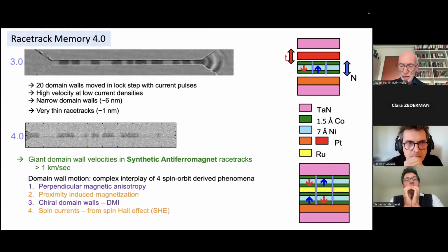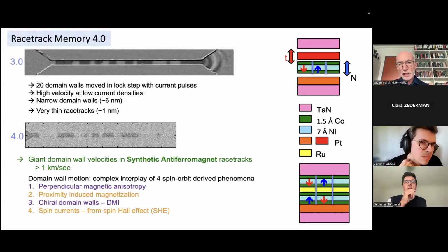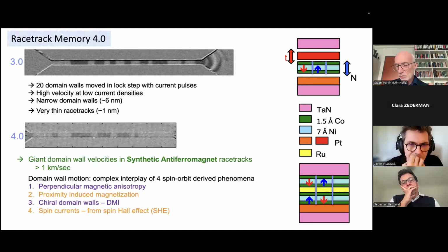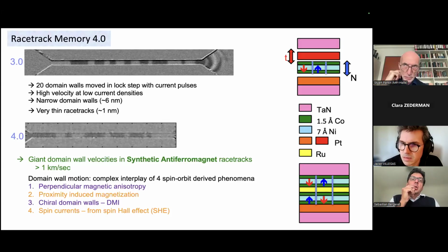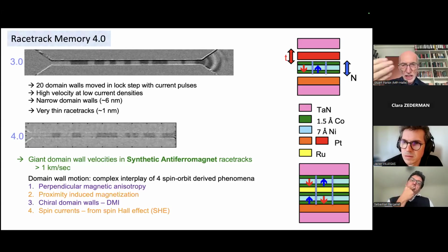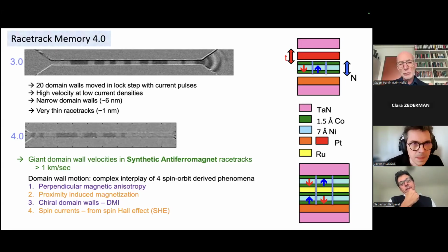Well, this is a brief introduction, and then I just wanted to mention that really all of our work for a number of years used optical techniques to detect the domain walls. So on the top here in 3.0, you can see a racetrack which is a few microns wide and tens of microns long, and the black and white correspond to the Kerr signal that we detect. The Kerr signal is a magneto-optical Kerr effect where the polarization of light is rotated as it's reflected from the surface of the magnetic film, and the signal then is high or low, depending on rotated to one direction or the other, depending on the magnetization direction. So in fact, as you can see here, we take a static picture of the domain walls, and then we apply current pulses and take another static picture. This is how we determine the domain wall velocity.